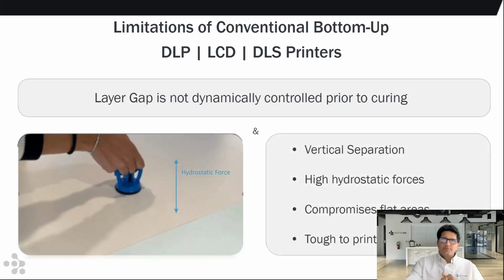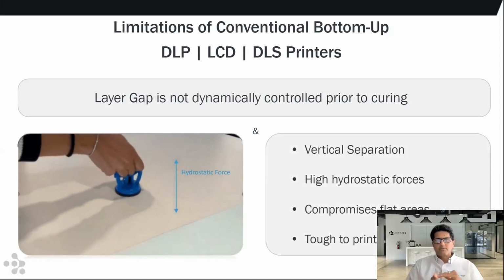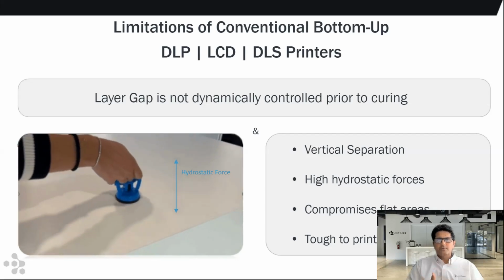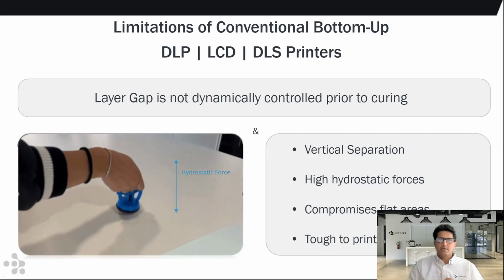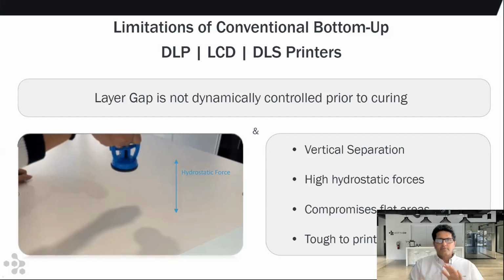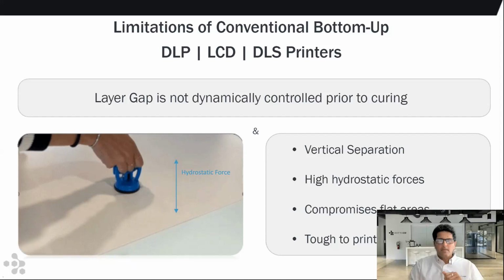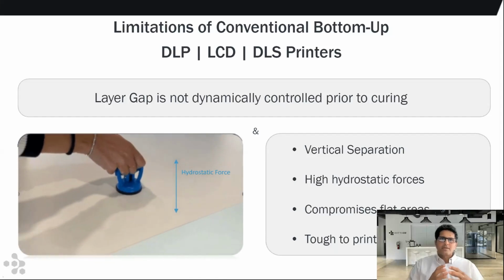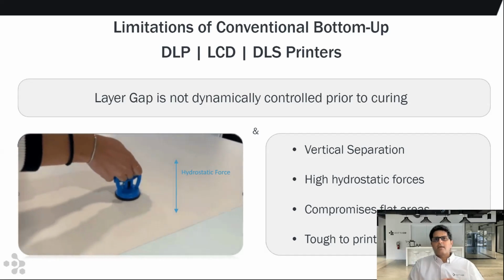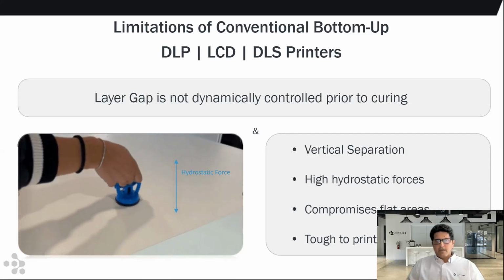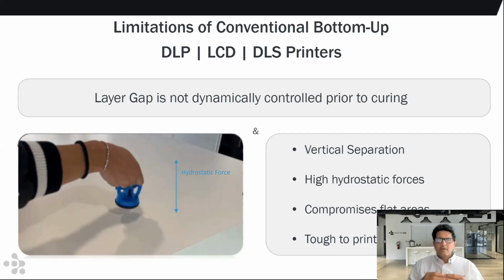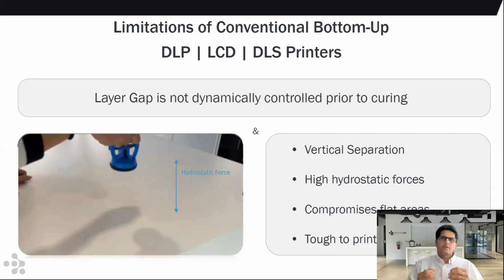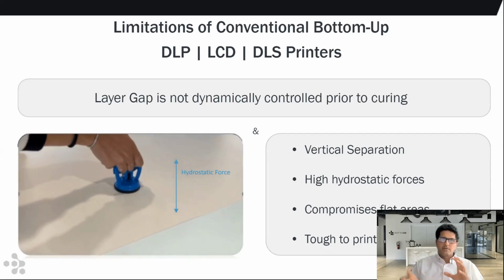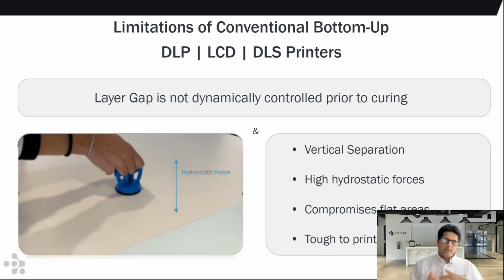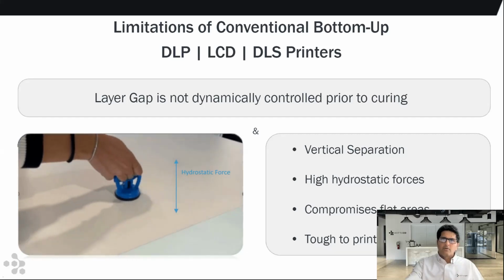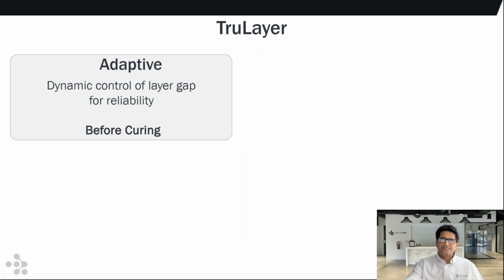So let me open up the slide. Once the layer is cured, the issue is the fact that there is a peel-off force that happens, and there's a big hydrostatic force that gets generated between the layer and the film. And that really compromises the layer and the flatness of the layer and the quality of the layer. So these are two inherent limitations where the gaps are not consistent before curing, and it's difficult to peel off the layer after curing. And that has led to DLP products being limited in the sense that you can either build small parts or you can build lattice structures, or you have to deal with the compromised layer and do finishing on the part later. So the goal here was now to really solve this problem as well.